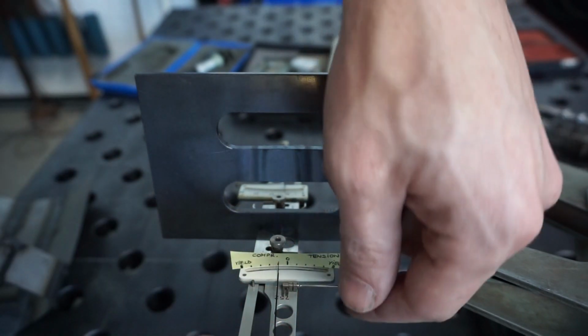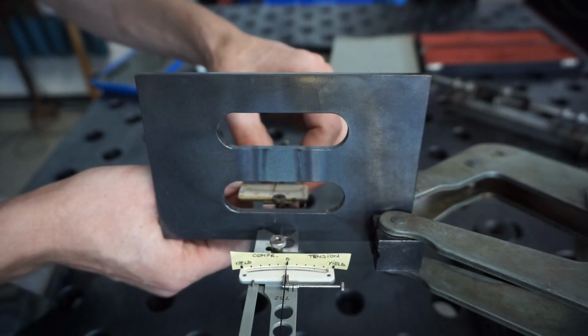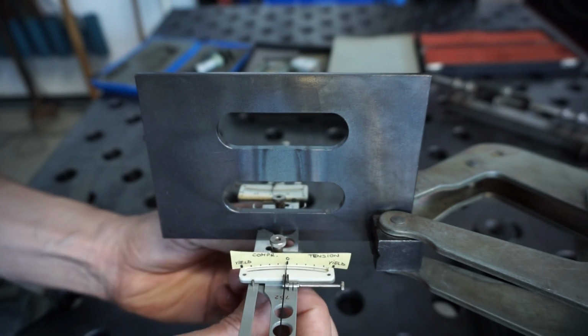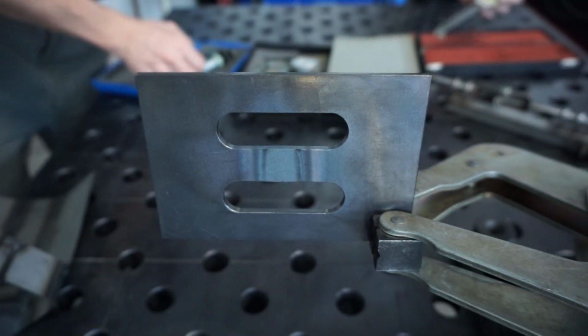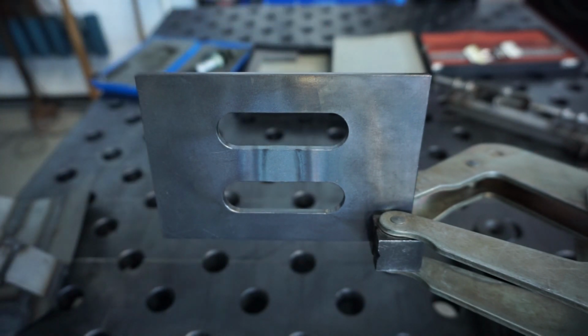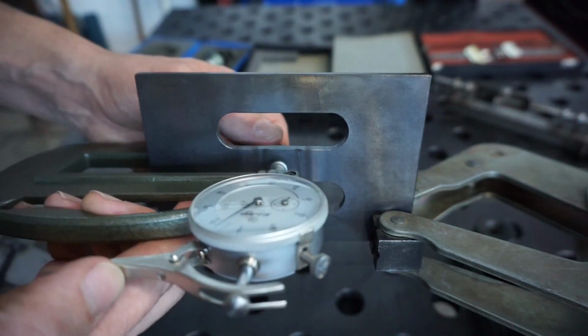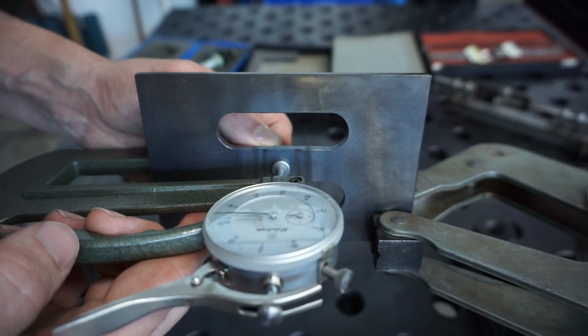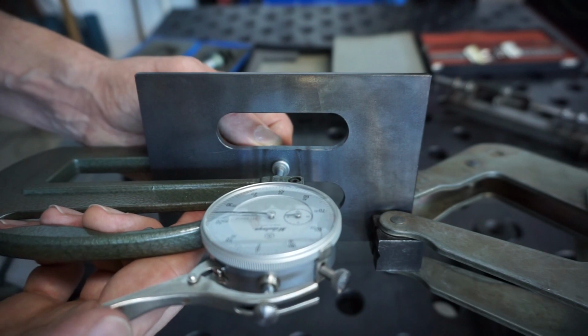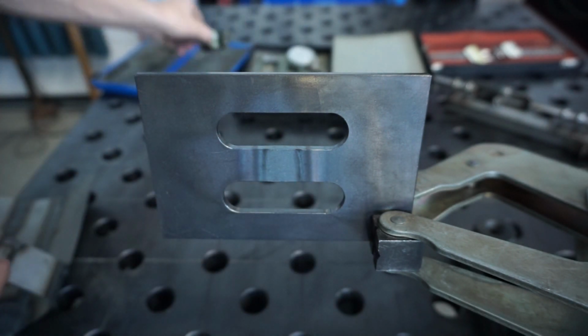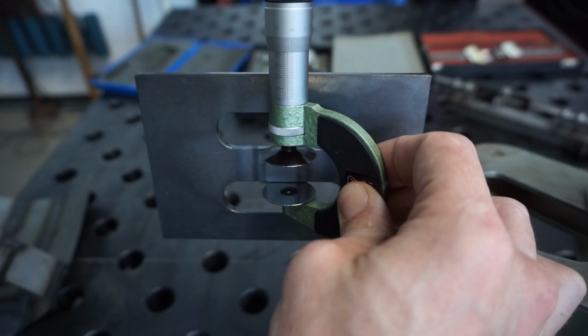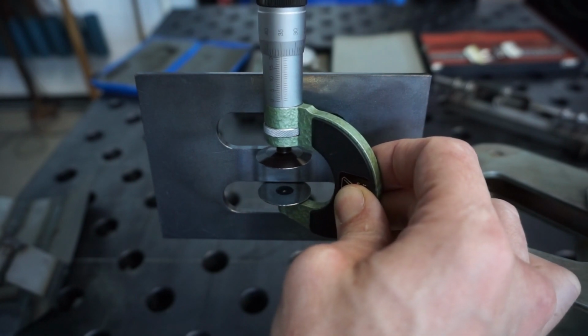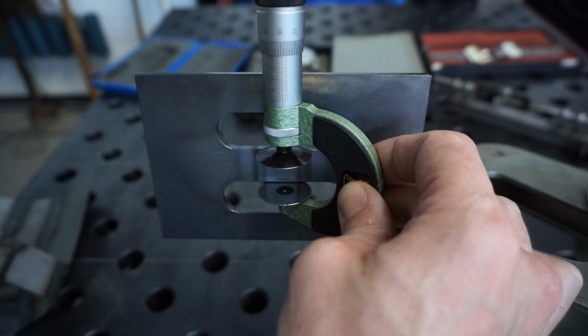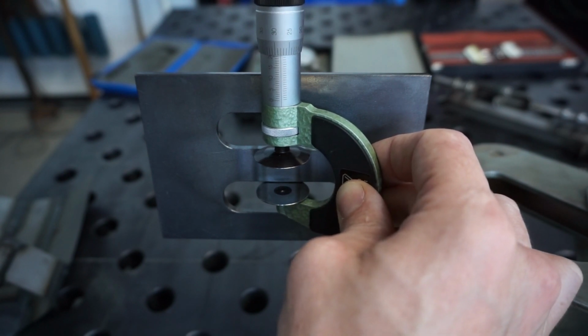If you recall, in the last episode we found out that local heating caused thickening of a sheet sample. The analogy we used to explain this behavior was the rising cake in the cake tin. Let's see what happened with the heated central bar. So thickness now is 5.23 millimeters, and width of the central bar is 20.28 millimeters.